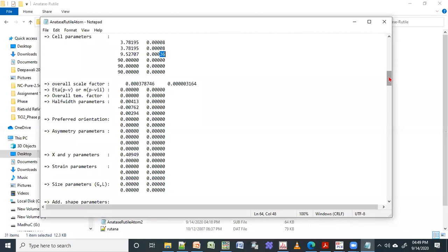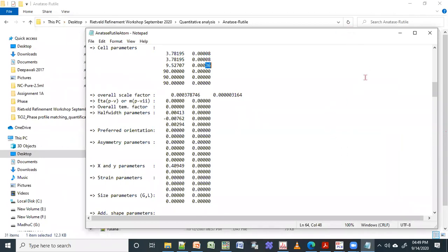It depends. See, because if you are doping, sometimes you may increase the crystallinity. Sometimes you may increase amorphous, like it can go more less crystalline. So if you are increasing the crystallinity, then your chi square can go better sometimes. And if you have a lot of strain in the samples due to doping, then when you go from pure phase to doped phase, as you increase the doping, your chi-square is going to increase. So it depends on what you're doping and all those things. Everything will have some kind of information, but you should know how to interpret those things. Okay.